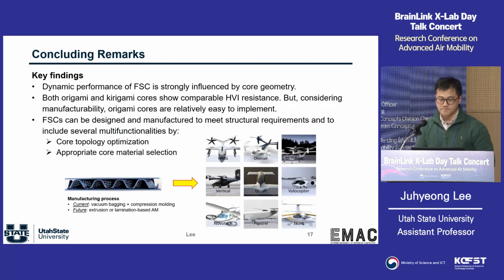So concluding remarks. We want to evaluate the dynamic performance of the fold core sandwich panel, and all the testing results and numerical predictions showed these are highly influenced by the core geometry. And both origami and kirigami cores can be used, and of course they have comparable hypervelocity impact resistance. However, if you think about manufacturability, origami is way easier to make. Of course, you can make a very beautiful kirigami core-based structure, but that may be super expensive.